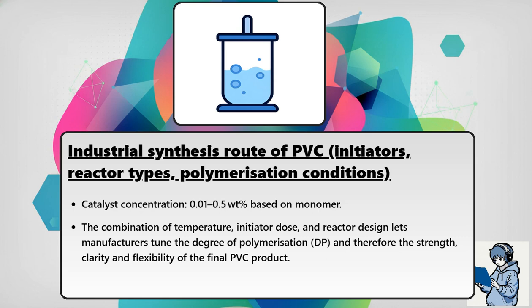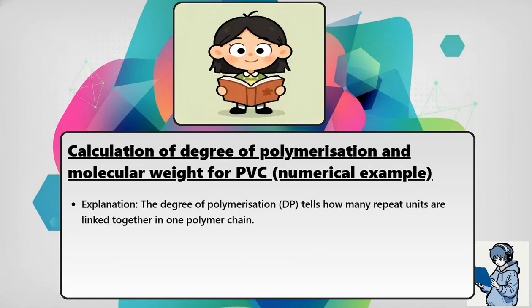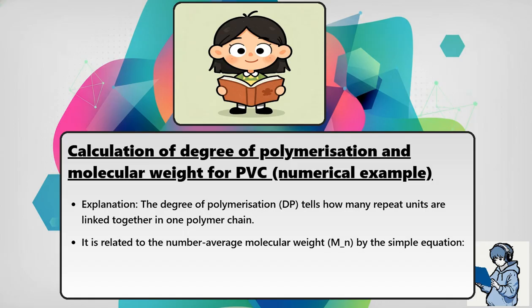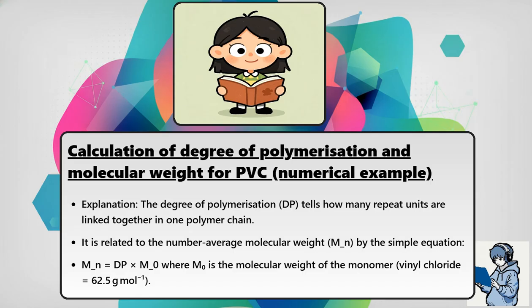The combination of temperature, initiator dose, and reactor design lets manufacturers tune the degree of polymerization, DP, and therefore the strength, clarity, and flexibility of the final PVC product. Explanation: the degree of polymerization, DP, tells how many repeat units are linked together in one polymer chain. It is related to the number average molecular weight, Mn, by the simple equation Mn equals DP times M0, where M0 is the molecular weight of the monomer. Vinyl chloride equals 62.5 grams per mole.